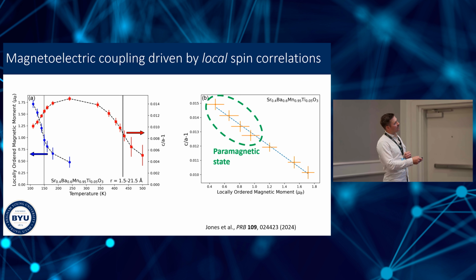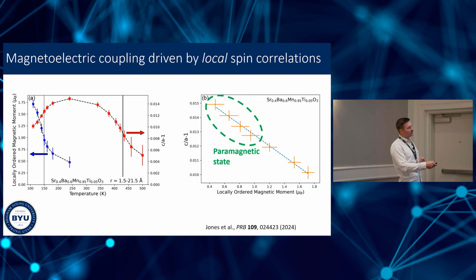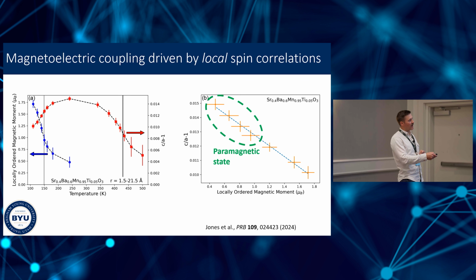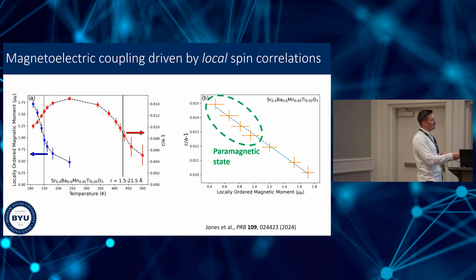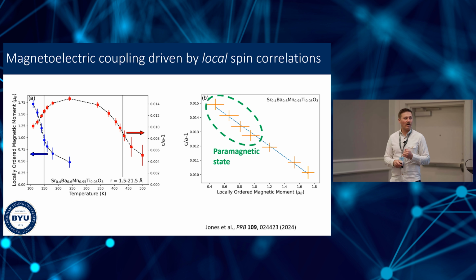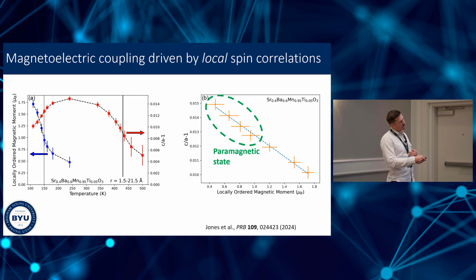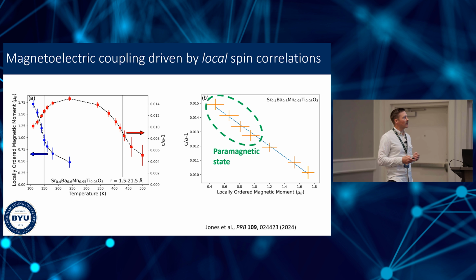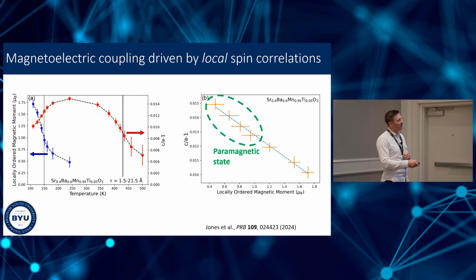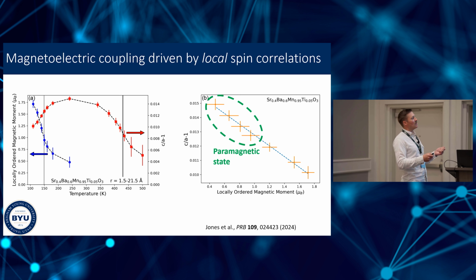The C over A ratio begins to turn over, which again, that's our evidence for the multiferroic coupling, the multiferroic behavior, as soon as the short-range magnetic correlations are kicking in. Okay? So let's do the same thing where we plot C over A minus 1 versus this local magnetic order parameter. A nice negative linear correlation. So again, this is that multiferroic behavior where the development of magnetic correlations drives a change in the electric polarization. All right, in this case, decreases the electric dipole moment. And these 4 data points were collected in the paramagnetic state. All right, there was no long-range magnetic order.